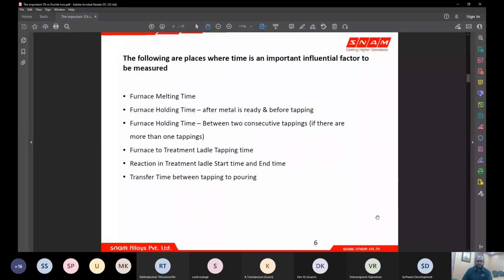So this is influenced by the previous time which we measure. If we are able to see that a particular alloy with X% magnesium is going to be violent, based on the amount of magnesium present and the process we are going to carry out, say open ladle or closed ladle. And when your tapping time is going to vary, your reaction start timing is going to be very early and it will end very quickly, because you don't have enough liquid metal available to subdue the reaction, so that the reaction can happen slowly. So the reaction start time and end time for a given alloy for a given process is influenced by your tapping time also. Every parameter which I show here is interlinked.